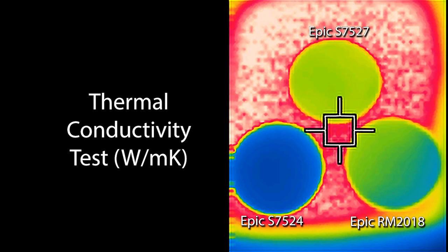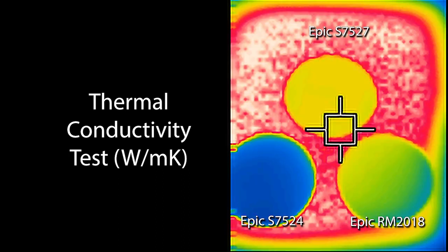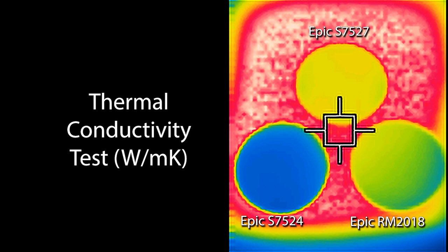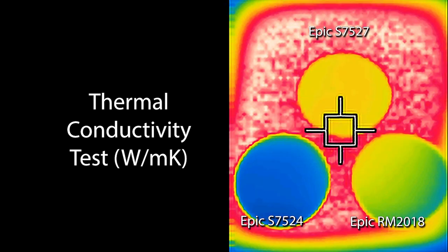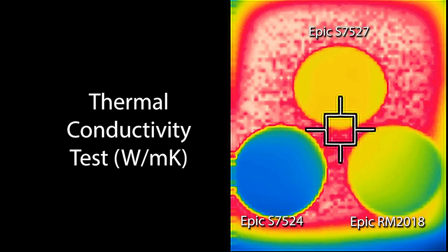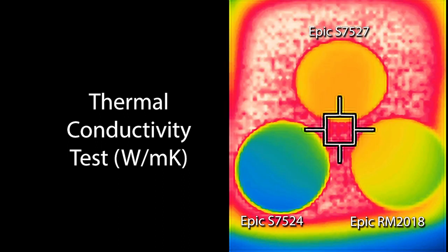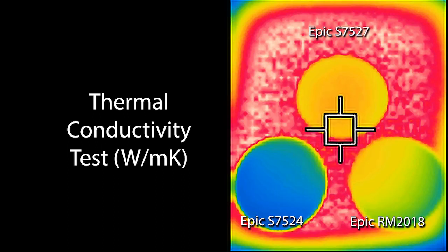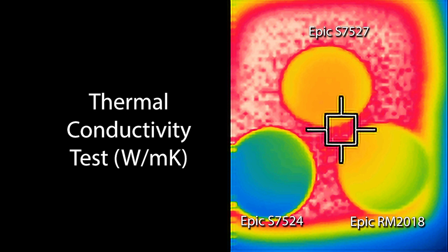The infrared image shows as the pucks are heated from the bottom, you can see that the S7527 gets hot faster than the other 2, indicated by the yellow color. Obviously, this shows that it is pulling heat from the hot plate faster than the S7524 and RM2018.